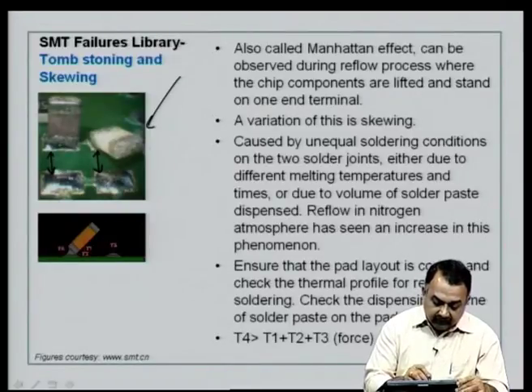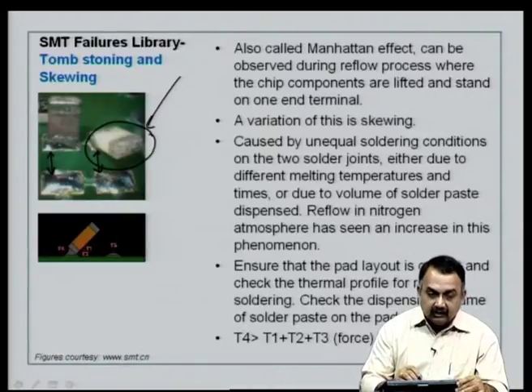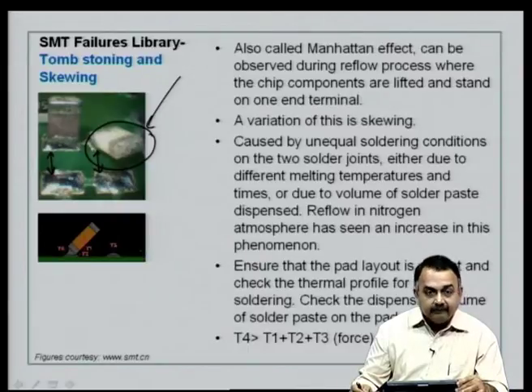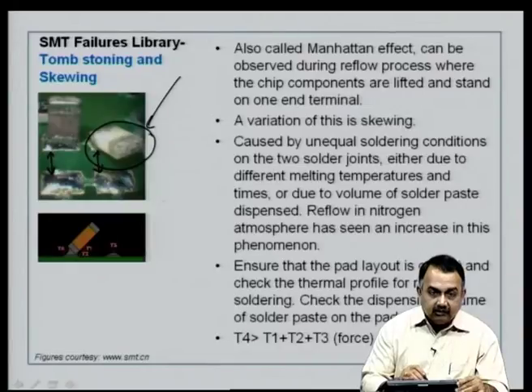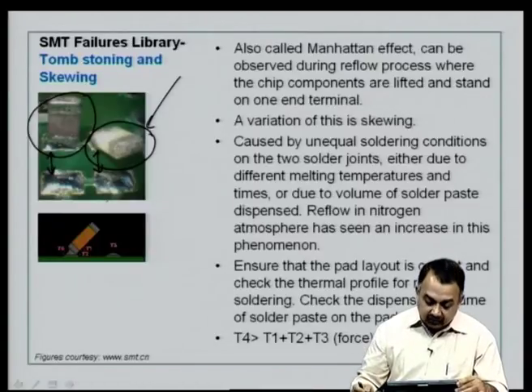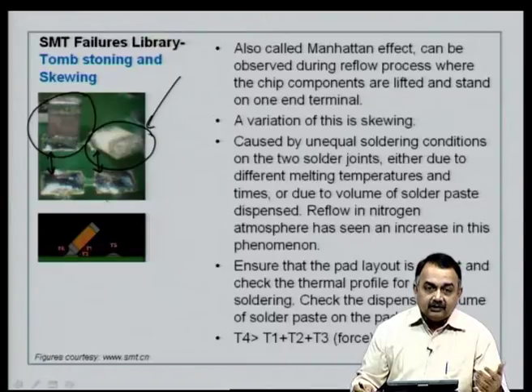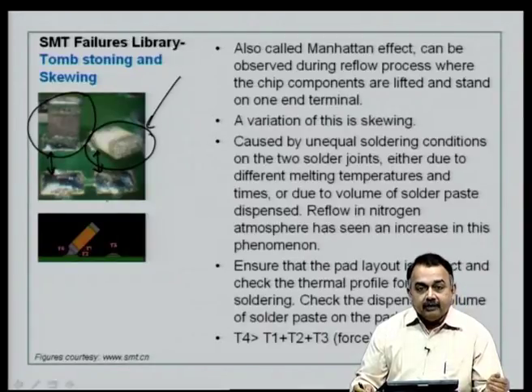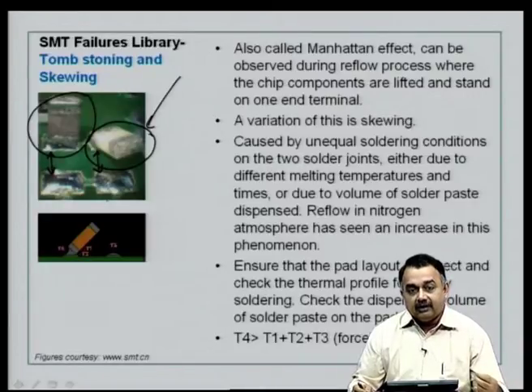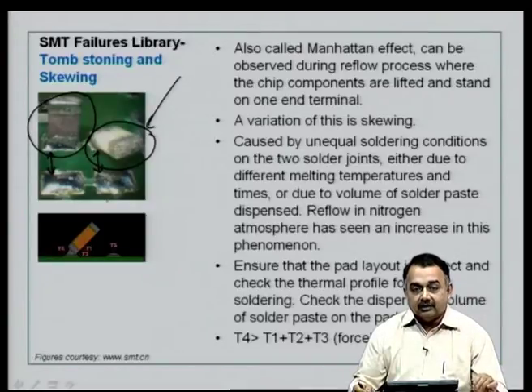Now, in this picture you can see that one component has lifted from the pad of the printed circuit board, and then it has skewed a bit, and in the other case you can see that it has lifted fully and it is standing as a tombstone. Hence the name tombstoning effect or skewing effect. Now, this can be observed during the reflow process, where the chip components are lifted and stand on one end of the terminal, and a variation of this, as I told you, is the skewing that you see. And how is this caused? It is caused by unequal soldering conditions on the two solder joints that the chip component is supposed to be placed on and then soldered perfectly.